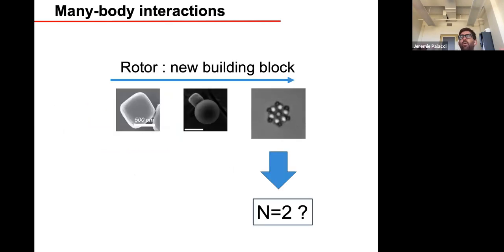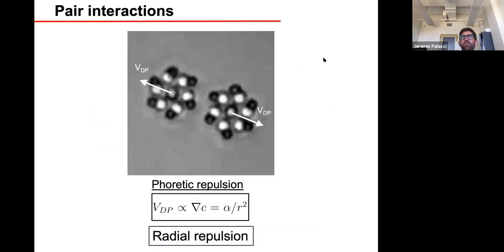So the question is, what happens for a pair of them? If you take two of them and bring them together, they just repel. The reason for that is that from a far field point of view, each one of these microgears is a sink of H2O2, and at this value of pH, it's repelling for particles. So those two microgears repel each other with the phoretic repulsion, which is the gradient of the concentration, which is 1/r squared.